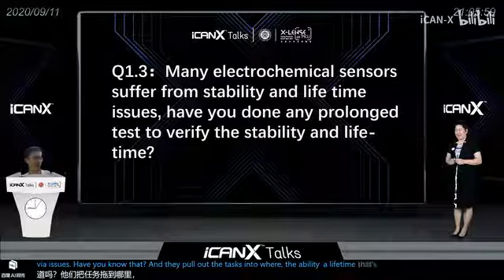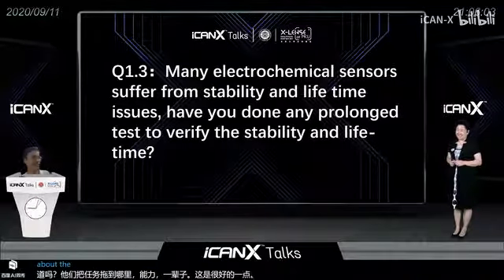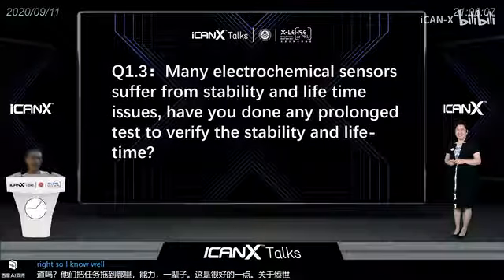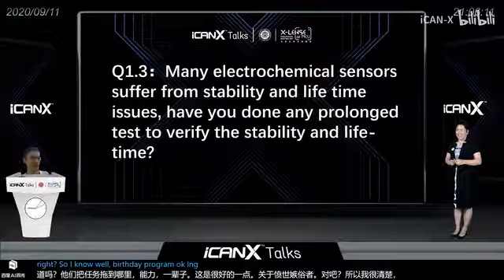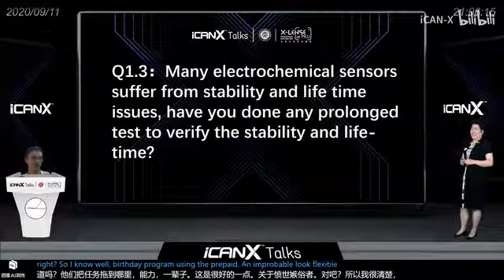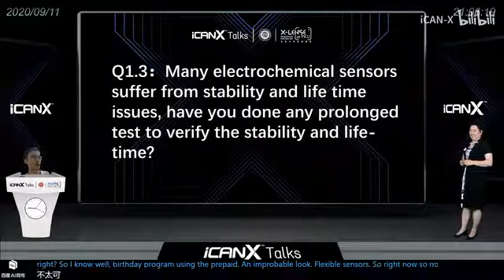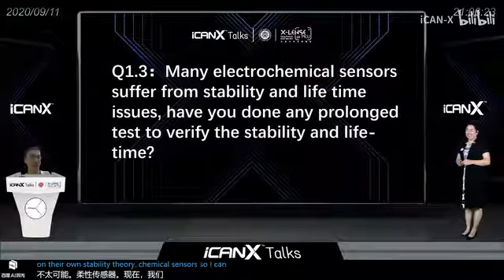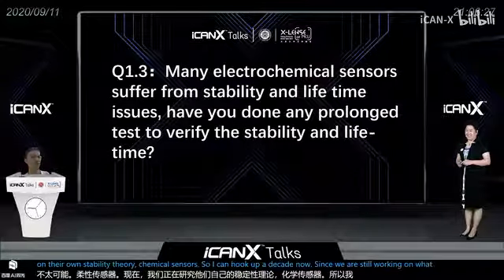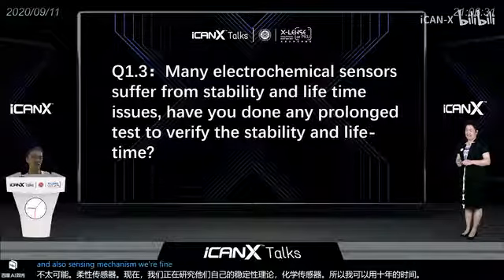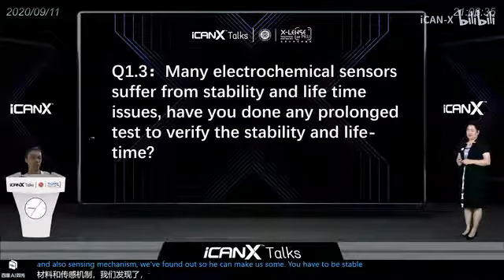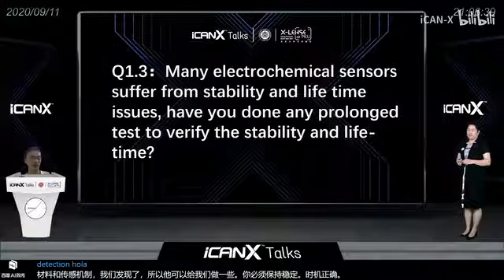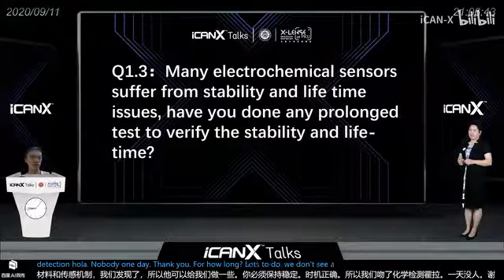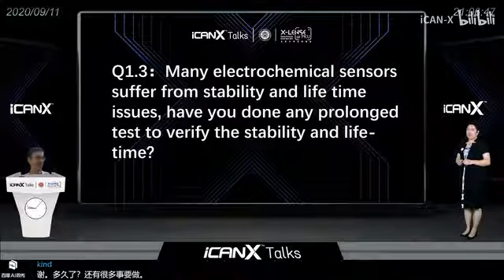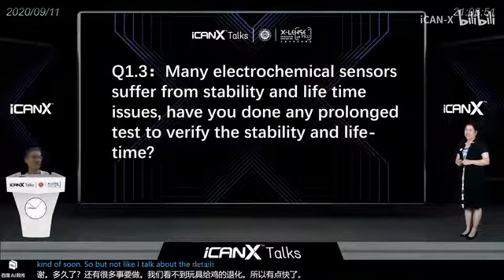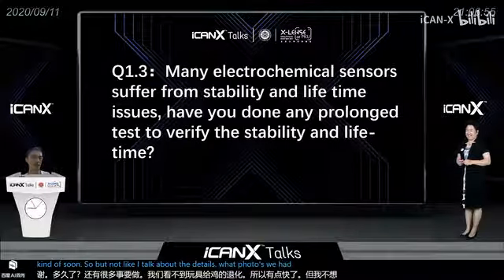Yeah, that is also a good point. Probably this guy knows well about chemical sensors. Drift is a problem when monitoring chemicals using printed and flexible sensors. Right now we are working on the stability of the chemical sensors. I cannot talk about details since we are still working on it, but by changing the material and sensing mechanism, we found that we can make relatively stable monitoring. We tested chemical detection for roughly 1 day, 24 hours, and still don't see any degradation or drift effect using that technique. It's coming soon, but now I cannot talk about the details. But probably there are a lot of other techniques to make a stable chemical sensor.